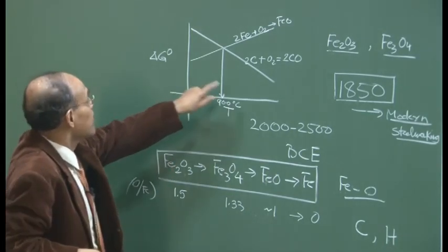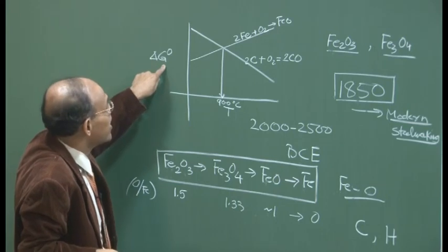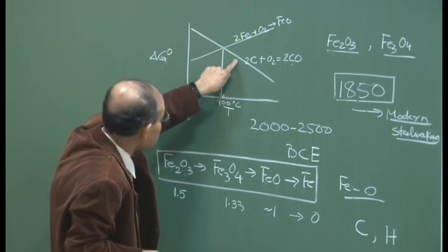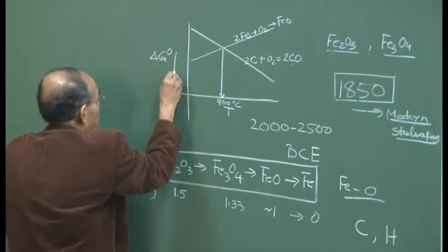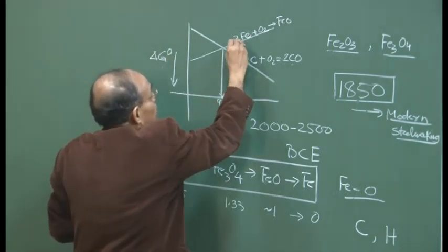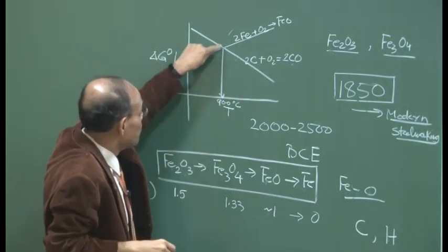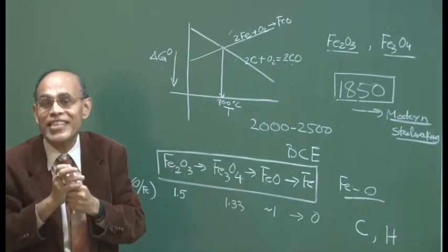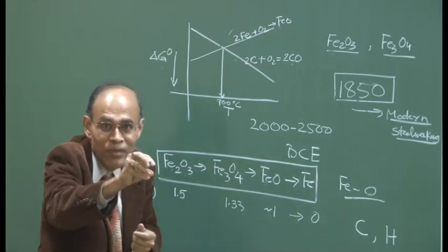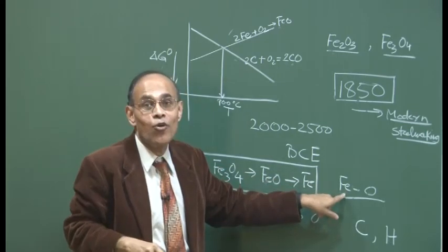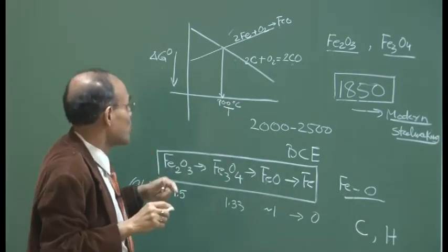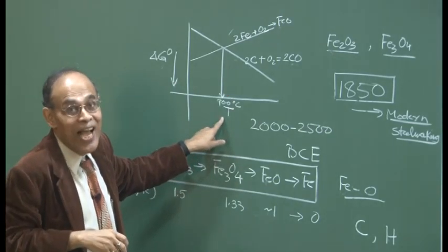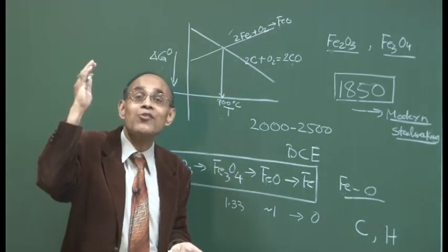The Ellingham diagram shows that this is the free energy change. So, the standard free energy change for carbon monoxide formation is less than that of FeO, it is more negative. So, the relative stability of iron oxide beyond 900 degree centigrade: FeO is less stable than CO. So, if I create a temperature of 900 or 1000 degree centigrade, then put some carbon in contact with FeO or Fe2O3, I will be able to isolate iron from iron ore. But creating that temperature 3000 or 4000 years back was not that easy. And this explains why people 5000, 6000 years back could isolate